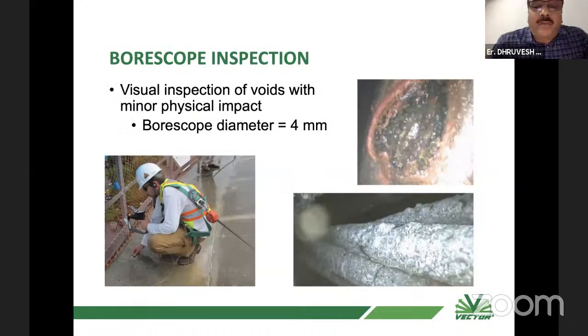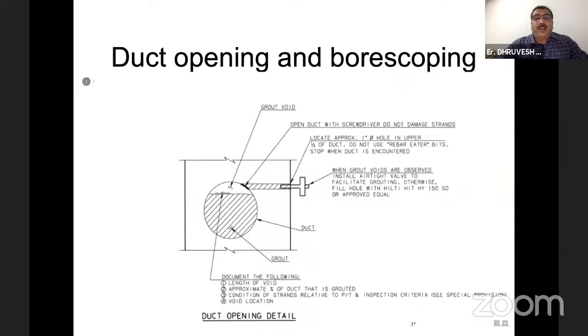Once you detect where the voids are, you can simply make a small hole up to the sheath, and don't use your drill to puncture the sheath. You can just use a sharp thing or screwdriver and make a hole, hardly 4 mm, and then you can insert the borescope probe inside the hole, and you can get a good view of the condition of the sheath inside. You can even have a video of the condition inside. This is a typical sketch that shows how to make a hole and then plug it with the right grout, or maybe you can use Hilti anchor resin grout to fill that hole back.